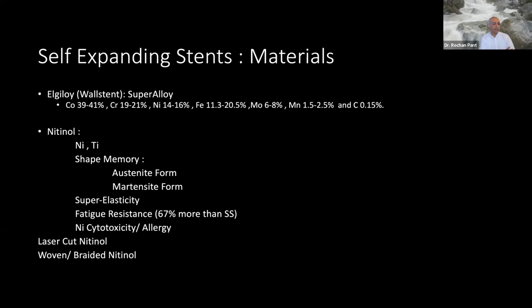Now, with self-expanding stents, there are two kinds of materials that are used mainly. One is Elgiloy alloy, which was designed for use in the aviation industry, and so it was very expensive, it's a super alloy, very strong. You can see the composition there, but it hardly matters beyond pointing out they all contain cobalt, chromium, and nickel. And this was used to design the Wallstent, and that is still in use today.